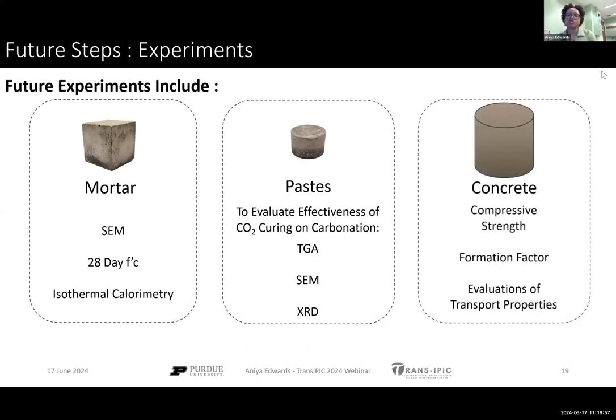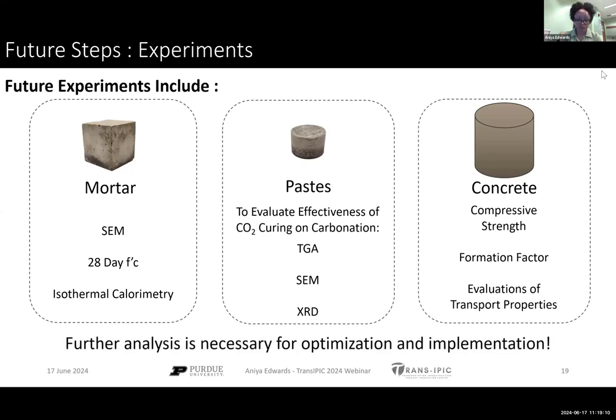And then for concrete, we're going to be looking at compressive strength, formation factor, and the evaluation of transport properties, particularly for reinforced concrete specimens. We want to see how nanomaterials and CO2 curing influence those. However, further analysis is necessary for optimization and implementation, so we have to keep doing research on this and see just how well it works.